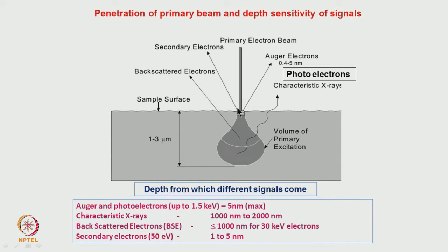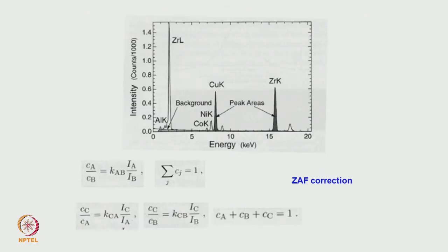region, whether it consists only of the precipitate or whether it contains precipitate and matrix, all this information is available. Whereas in an SEM we look only at the surface of the sample, we do not know the depth to which the second phase is present, because of which there are a lot of reliability issues regarding the composition which we obtain from different regions in an SEM. That issue is reduced considerably in the case of a TEM.